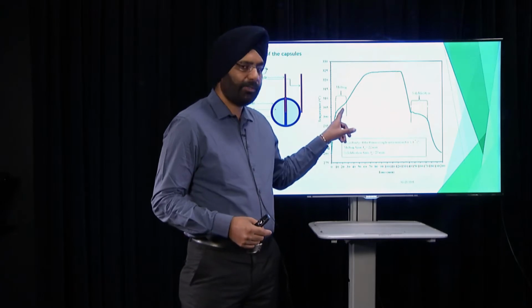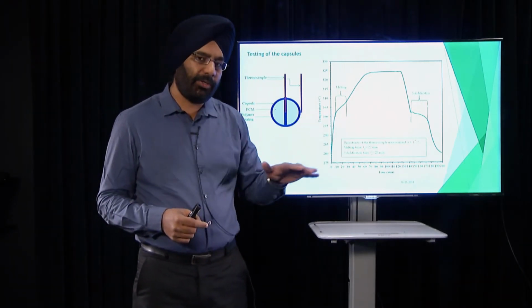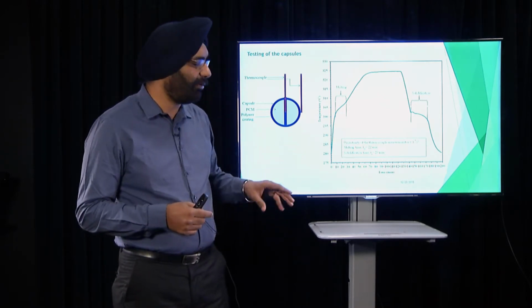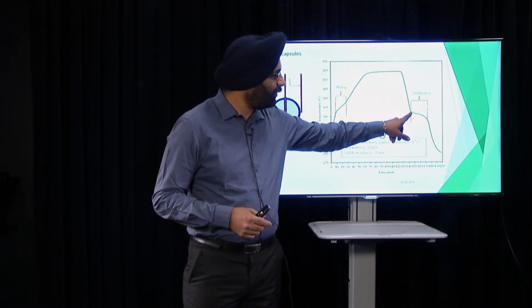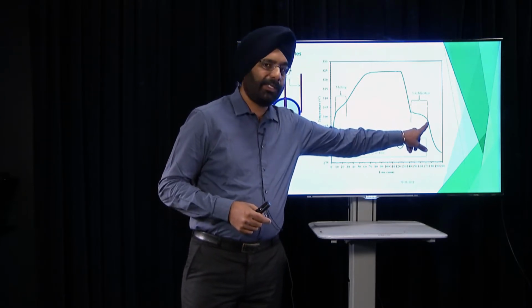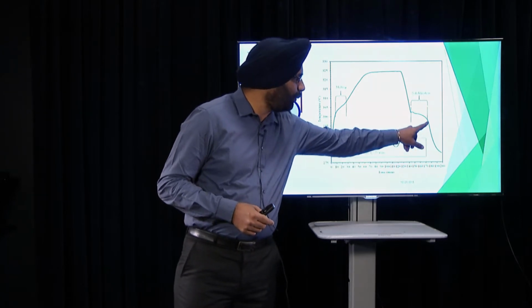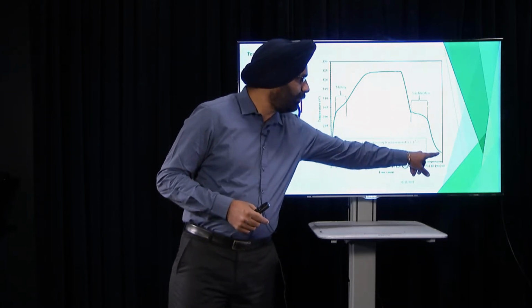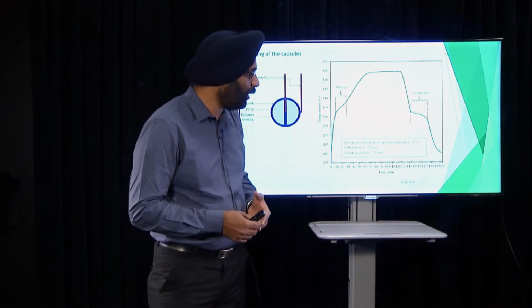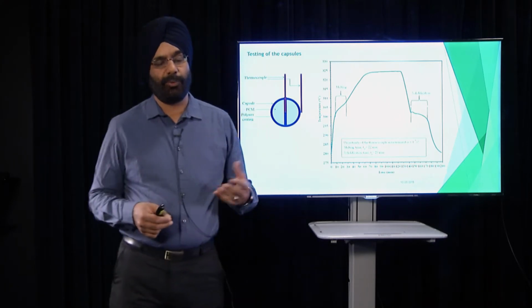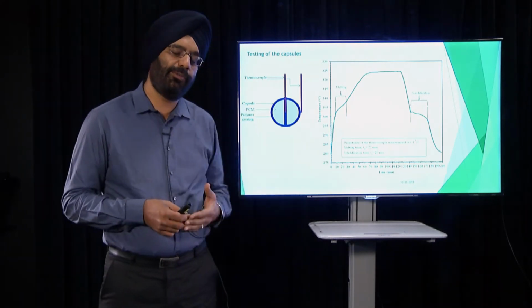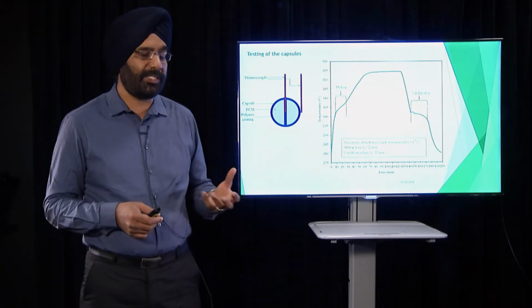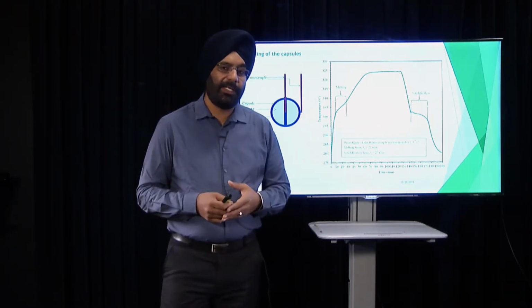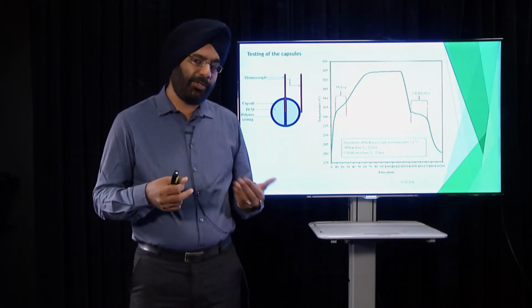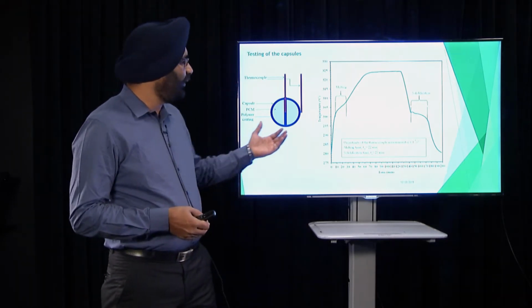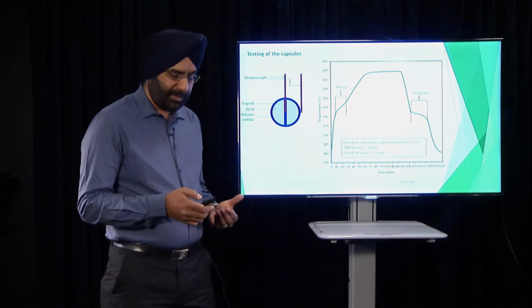It's at almost a similar temperature. There is 1 or 2 degrees difference. So it's slightly lower. That's called subcooling, but it's not that great. So the solidification starts from here, and then it ends up there. You will see immediately when the whole material got converted into solid, the temperature decreased tremendously. So the solidification time took 29 minutes. So we know that the capsules which we generate take around 22 minutes to completely charge and 29 minutes to discharge. And you will see here the solidification is taking longer than the melting, and it's because of the different phenomena involved in the charging and the discharging, in the melting and in the solidification.